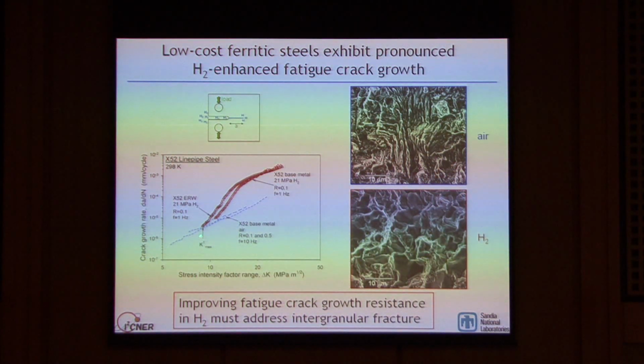If we measure the amount of crack growth per stress cycle, you can see that for tests done in high-pressure hydrogen gas, in this case 21 megapascal hydrogen gas, this is a low-cost steel designated X52, used in pipelines in the United States. You can see that at some critical value of K max, these crack growth rates start to increase quite dramatically, ultimately becoming about 10 to 100 times faster than the rates in air. So these cracks can be propagating through the walls of pressure vessels and pipelines much more rapidly than in an inert environment, and this is a concern for structural integrity.